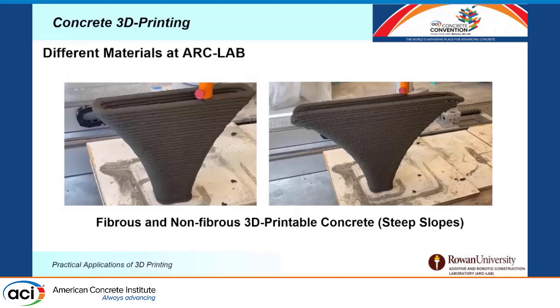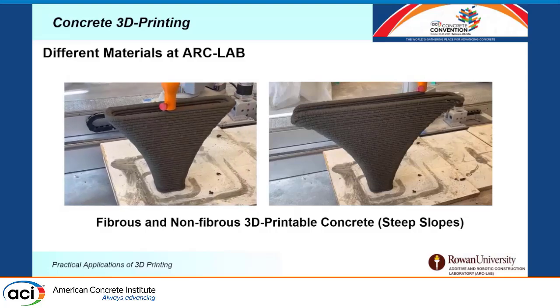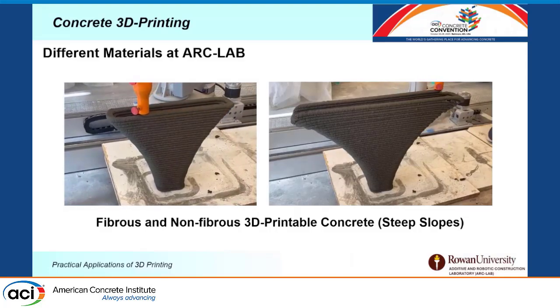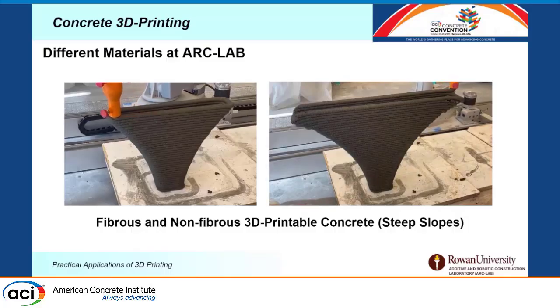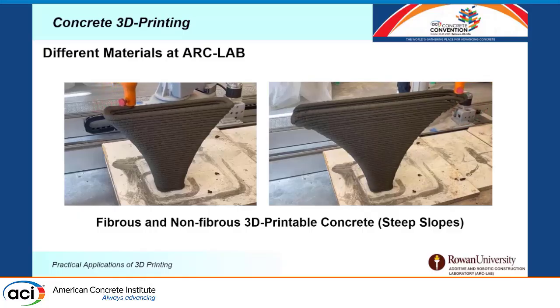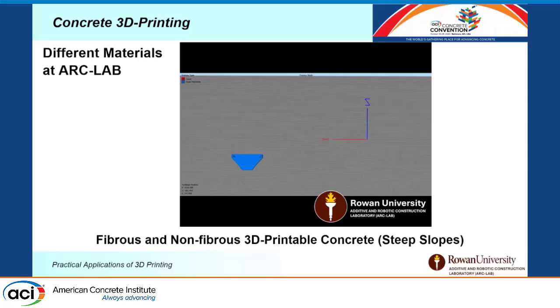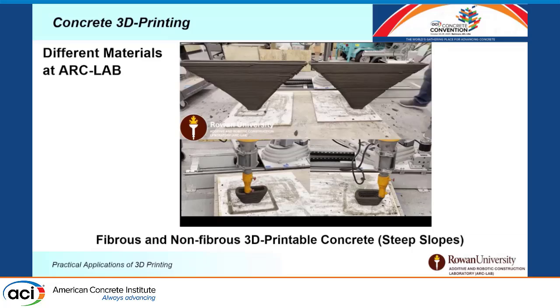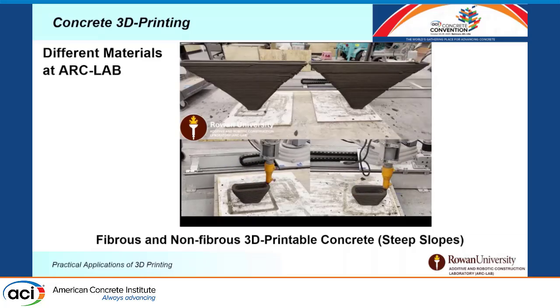As a conclusion, we have really nice 45-degree slopes on non-fibrous mixes, while if you add fibers, we are able to bump that to even 65 degrees from the vertical position. That could be useful for some practical applications, what we call segmental printing, where you can print back and forth 2 piers or a gated structure or arch structure, and after that join them with a top slab. So we did that last year, where we fed the material to the auger.